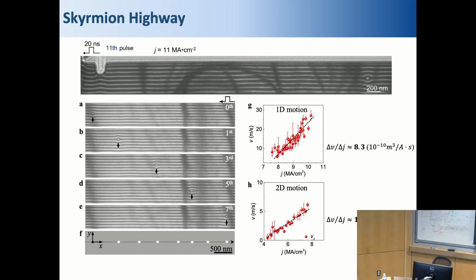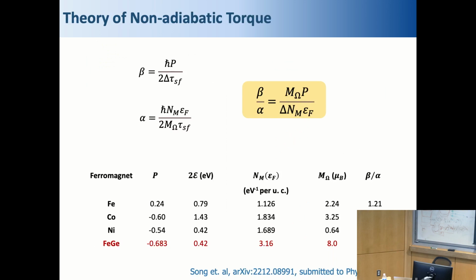If the current is even higher, then the skyrmion will move across the lane, because the larger the longitudinal velocity, the larger the transverse velocity, and the skyrmion will jump from one lane to the other. Or if your current is really very high, then the skyrmion will be annihilated. So there is a window here. And we also did some first principle calculations through modeling, and we confirmed that iron germanium has this beta over alpha ratio that is very large, almost close to 10. But for all other conventional ferromagnets, this ratio is about 1. So there is really a gift, I would say, from the iron.